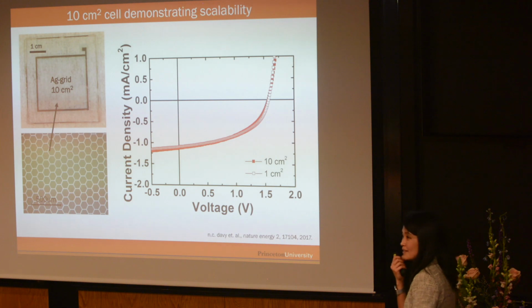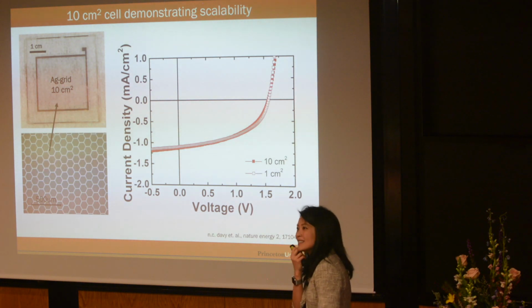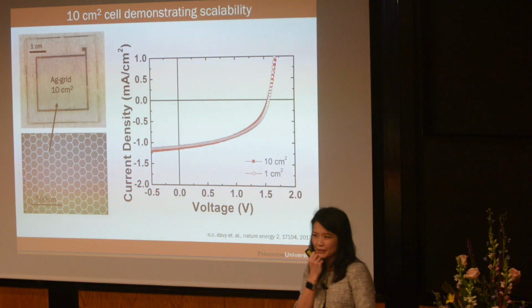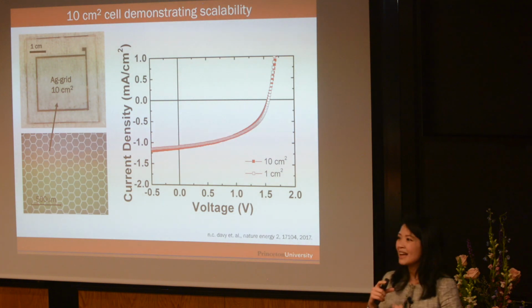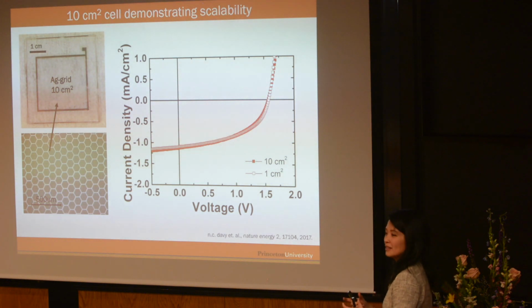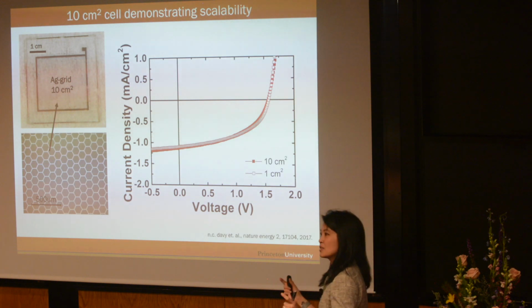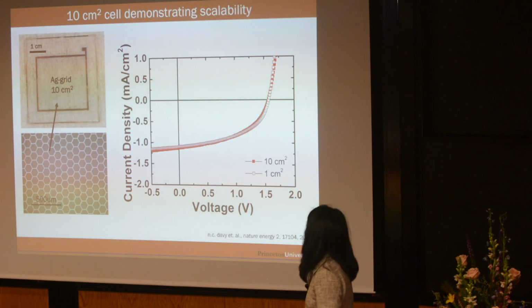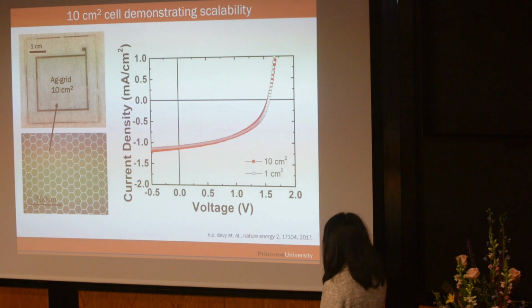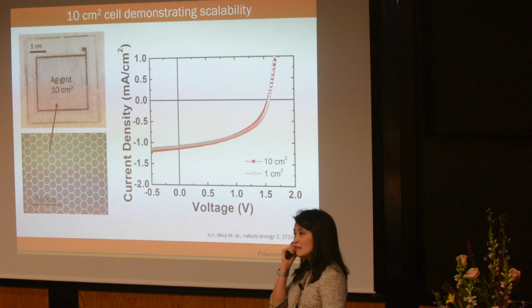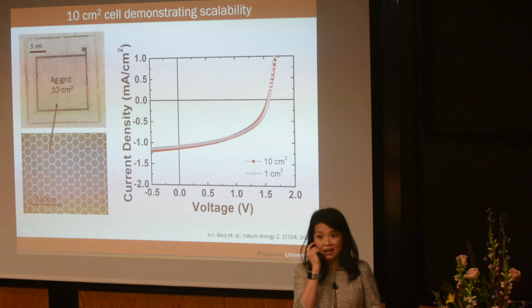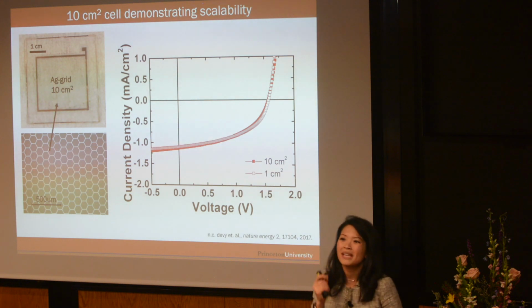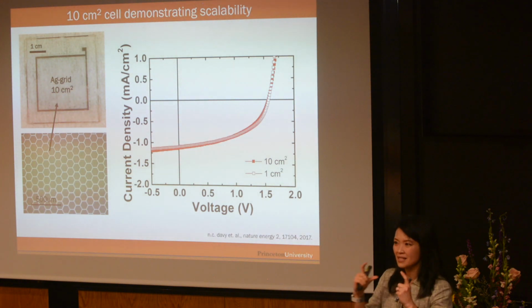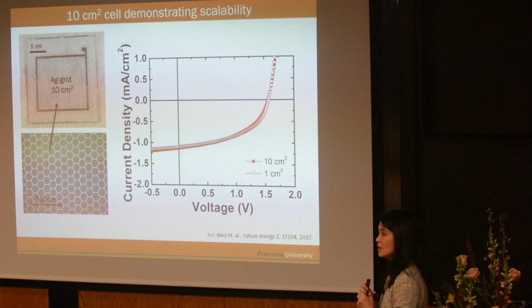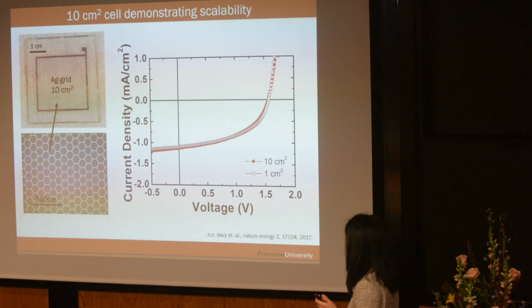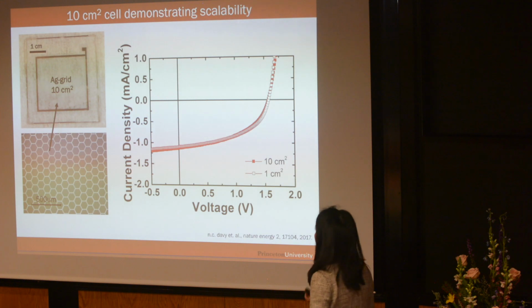Okay, so then we got greedy, and we said, okay, 2 centimeters squared is great. But you know, if you want to really make windows, you need to make at least a 10 centimeter squared subcell, because then you can stitch 10 centimeter squared subcells together to make a module. So we said, okay, we're going to set out and make a 10 centimeter squared cell. But the electrode that we were using, which is indium tin oxide, I mean, you can't extract charges effectively with a 10 centimeter squared indium tin oxide electrode because it's just not sufficiently conducting. So we had to re-engineer the transparent electrode.